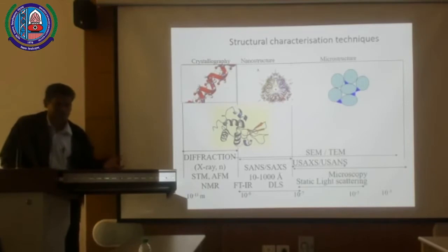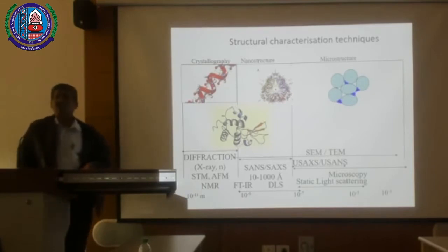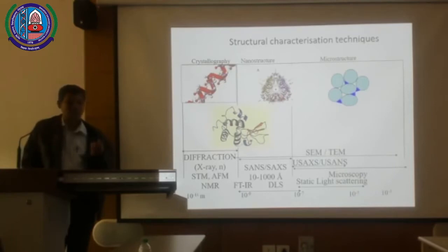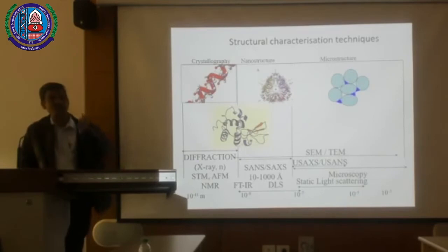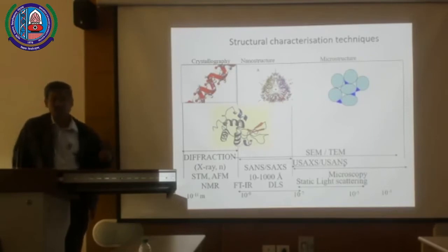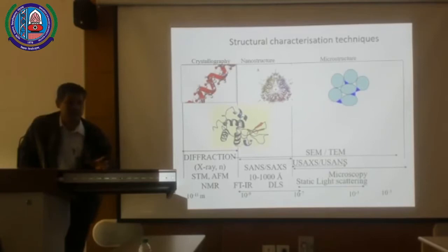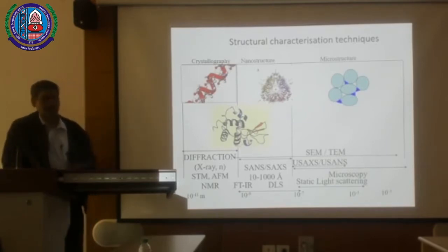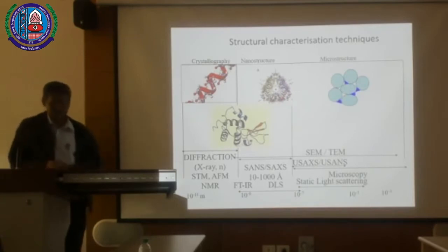That's a microstructure there. If you have pure amylose, the starch, and just put it in water and heat it constantly up to the gelation point, then you see that as the amylose is heated, the birefringence disappears, meaning it is completely gelatinized. You no longer have the form; the molecule loses crystallinity. So that's what the microstructure says.